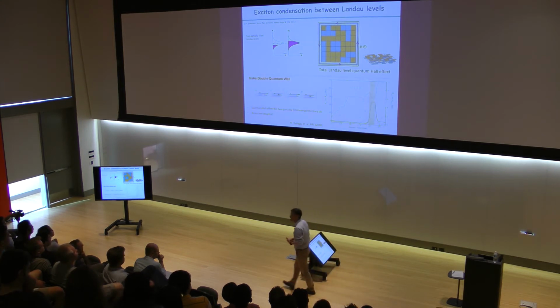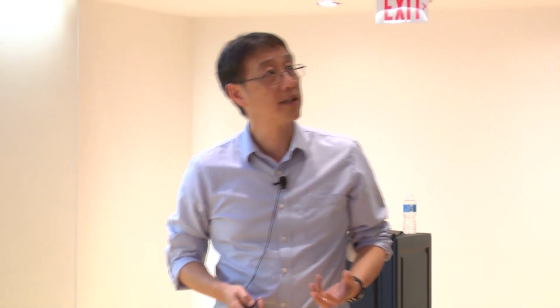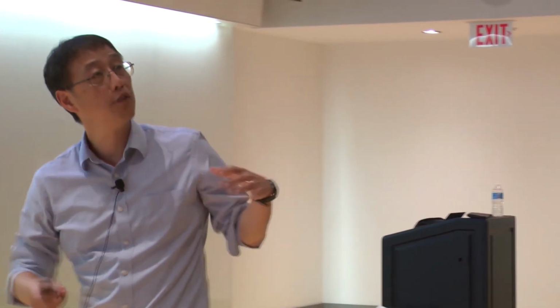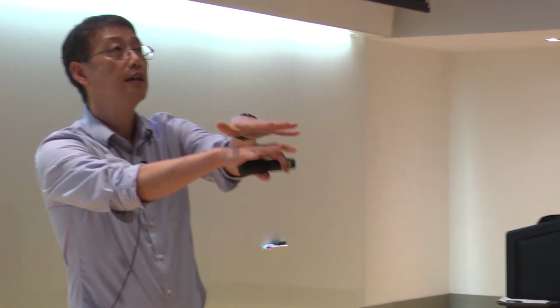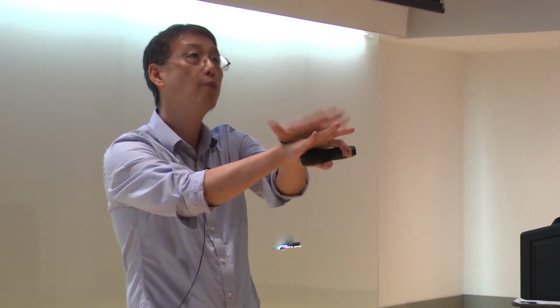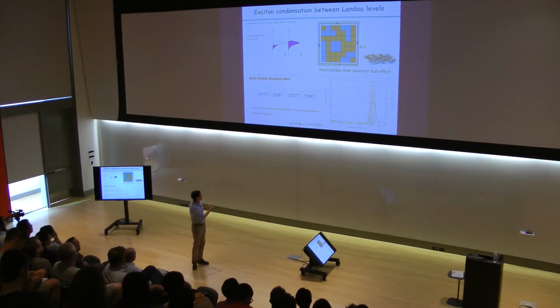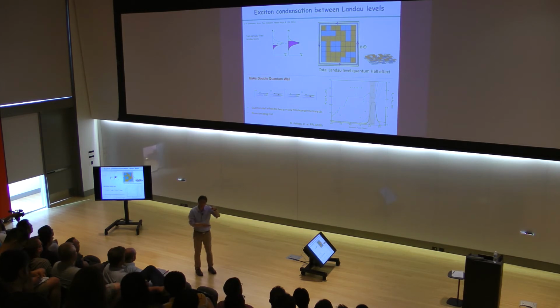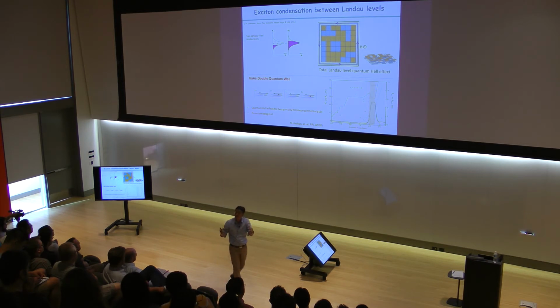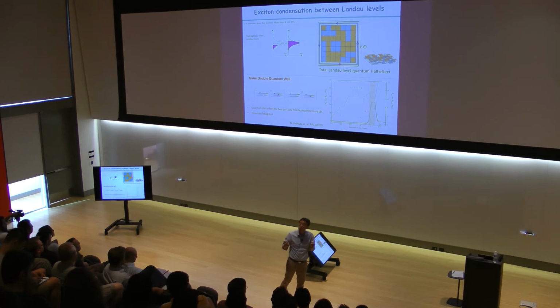And from the 90s, Jim Eisenstein's group at Caltech is basically the pioneer in this field. They demonstrated that when you have these two quantum Hall layers together, they start to talk to each other and form these quantum mechanically coherent states, which can be detected by carefully measuring the transport. For example, again you have two layers, you send the current in the top layer and just measure the voltage in the bottom layer and define the resistance. This is not the direct resistance. This is what we call the drag resistance. And they start to see that the drag resistance is quantized.